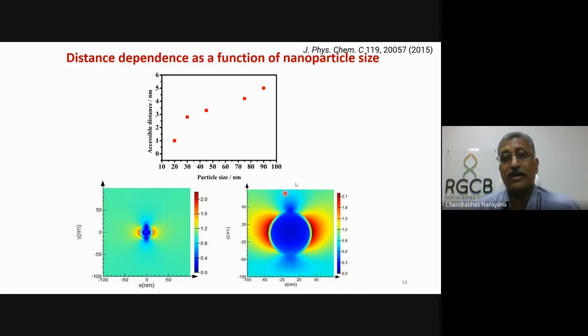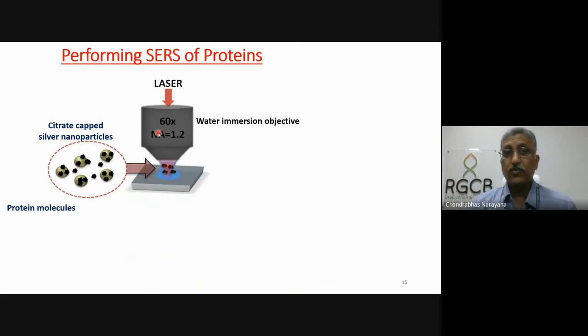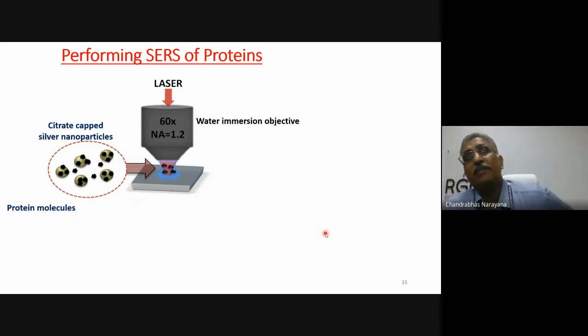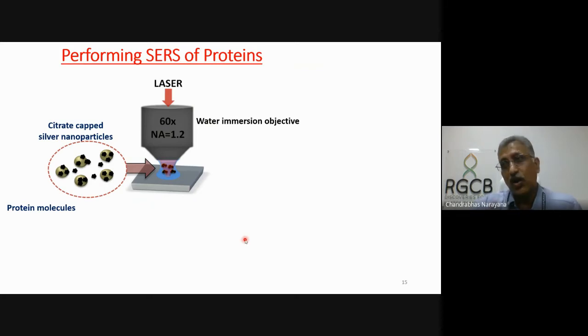And if you do a calculation by FDTD, you can see why it happens. When you have a smaller nanoparticle, the plasmonic effect, the electromagnetic distance, is very small. As you increase the nanoparticle, the distance actually increases. And you can see that it matches exactly what we had measured in our system. So when we do this with biological systems, we can do a very interesting set of problems. The next few examples will be based on how Raman can help you in doing various experiments. But before we go to the examples of application, we would also like to show you how we make new nanoparticle structures for doing these experiments.